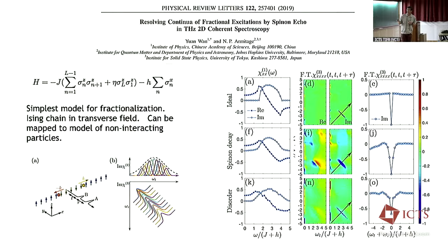If you put in lifetimes, you see that there's kind of broadening here, as you might expect. If you put in disorder, there's no broadening at all. The linear response is basically indistinguishable from each other. And the point we made is that you can tell the difference between spinon decay and interactions versus disorder. You can't tell at all in the linear response, but you can tell in the nonlinear response.